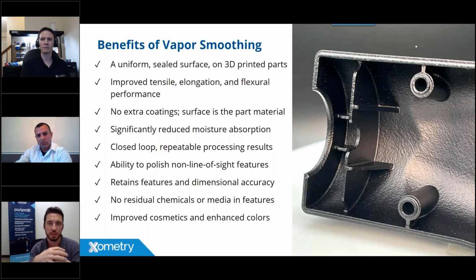Those peaks and valleys are evened out, and some of those valleys tend to be crack initiation sites in the powder technology, which is a point of failure if it's exposed to different stresses, or the separation between layer lines in filament printing, for example. That's always going to be the weakest spot, in that Z direction, because it's not actually melted together completely. So what vapor smoothing is doing is removing those flaws in the surface, removing the layer lines in FDM, and actually creating almost like a skin on the outside of the part that creates a much stronger outside. So now we're able to improve elongation at break because these failure points have been removed, and also maintain tensile strength, and in some cases even increase tensile strength. So now we're taking these carefully engineered materials and elevating them to new heights just because of vapor smoothing them.